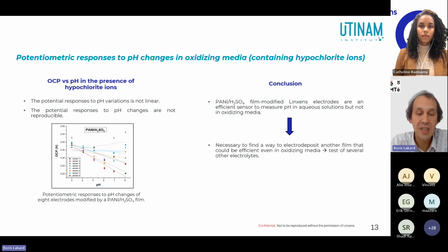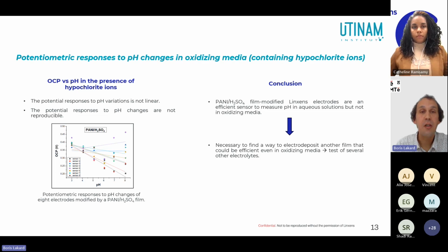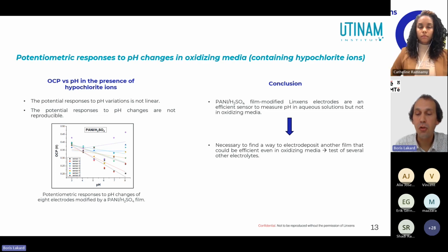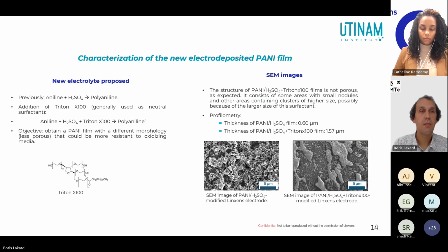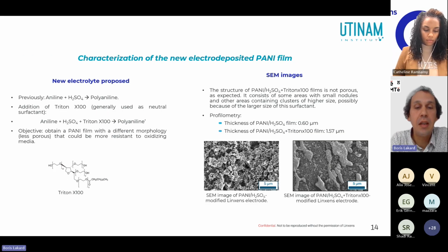So to briefly conclude with this part before the end of the study, it can be stated that the polyaniline-based Linxens sensors were effective in aqueous solution unless the medium was highly oxidizing. To improve the situation, we decided to change the electrolyte and added different surfactants in the electrolyte solution to obtain a more compact polymer film that could resist more to the attack of the film by hypochlorite ions. The best results were obtained using the Triton surfactant.